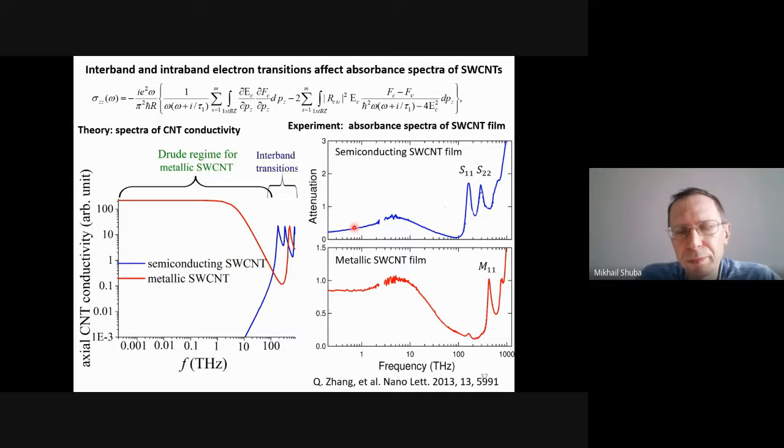And in the low frequency part, we can see the non-Drude behavior of the effective optical density of the tube. So there is a broad resonance in the terahertz range, and this resonance originates from the geometrical resonances of the surface wave in carbon nanotubes.